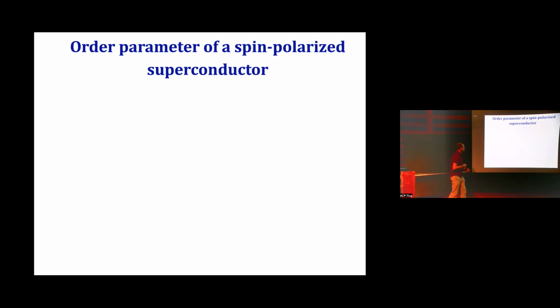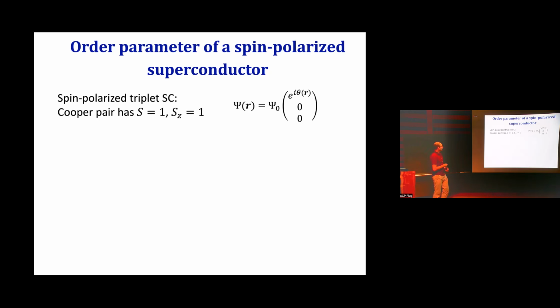Okay, what's the order parameter of a spin polarized triplet superconductor? So it's a particular type of triplet superconductor that's occurring in this graphene system. If you have a triplet, as you all know, I can have a triplet which means total spin of the pair is equal to 1, but I still need to specify whether SZ is 1 or 0 or -1. This is a fully spin polarized superconductor, which means that the total spin along some quantization axis is actually 1. So the order parameter is just like a spinor of spin 1. It has a direction, say +z, and it has a phase, because the superconducting order parameter is always a complex order parameter.